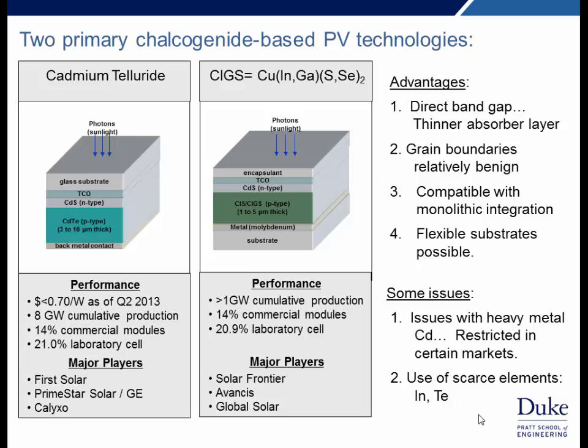With this in mind, we can first take a look at the two dominant chalcogenide-based technologies, cadmium telluride and CIGS. The reason for looking at these is that they offer a number of advantages. They're, of course, direct bandgap semiconductors, so we can use very thin layers. Their grain boundaries are relatively benign with respect to recombination, meaning that we can use polycrystalline films rather than needing single crystal layers and still hope to get high performance. They're compatible with monolithic integration, which again should help lower cost.